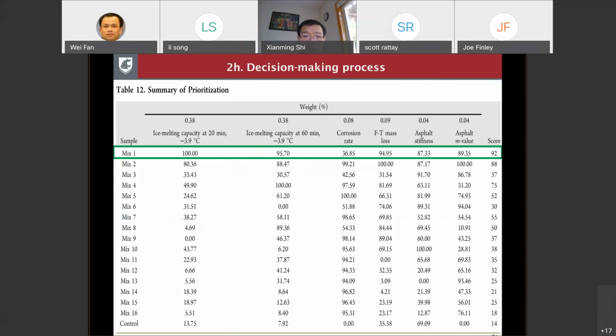And then we look at, okay, as an agency, how do we make a decision? So given a set of user priorities, we can develop some decision weights for each dimension of the problem. And then we can come up with a process to derive a composite index or score. So the best performing one, as you can see here, the mix one, had a score of 92, which is out of 100, not too bad. When we look at the control, which is straight salt brine, we have an index or score of 14.